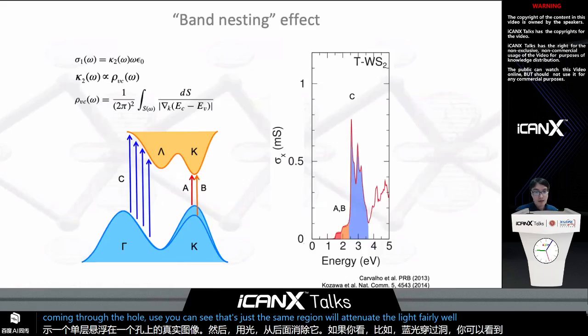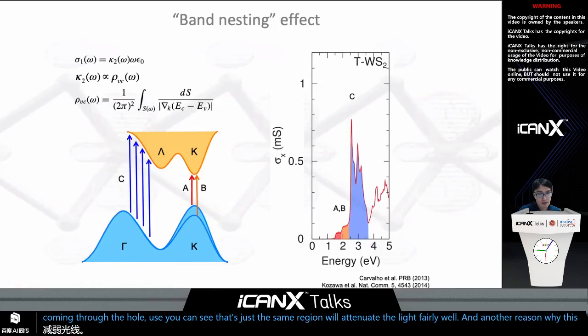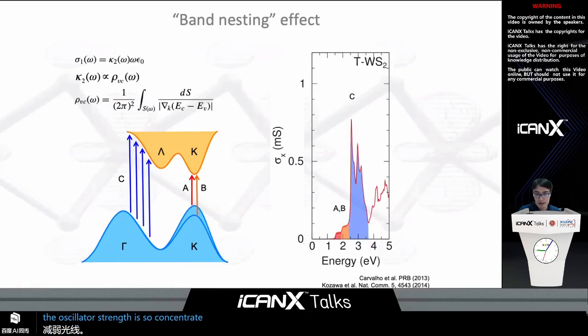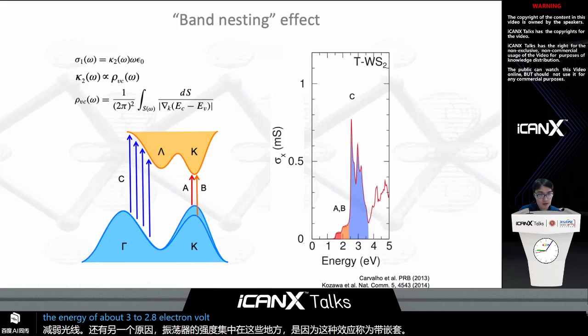And another reason why the oscillator strength is so concentrated in these resonances is because of this effect called band nesting. This happens around the energy of about 3 to 2.8 electron volts, which is in the blue range. So this is also a dimensionality effect.